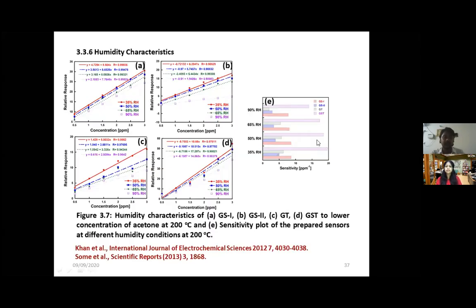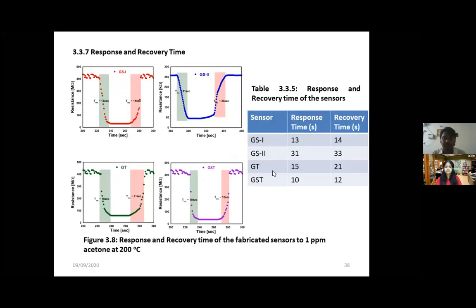So we need a humidity compensation method, or we need certain desiccants in the mouthpiece so that the humidity is eliminated. And this is the response and recovery time. It is 10 seconds, 12 seconds, which is quite fast compared to other literature and the existing analytical techniques.